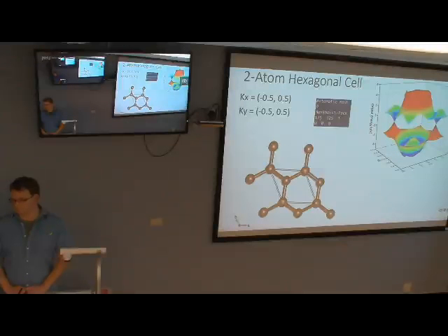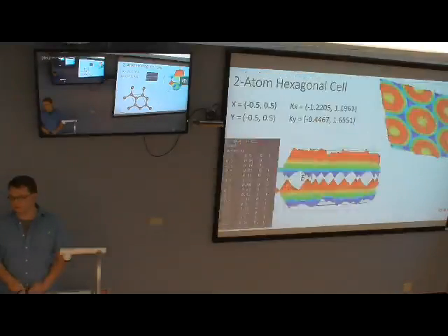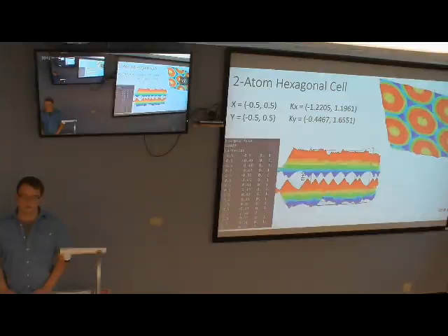Yes, and it especially does not characterize the points around all 6 Dirac points. Because here it shows explicitly 2 where they almost touch, right? But there should be 4 more. And so by manually choosing the k points, I can visualize all 6. One may need to fiddle with which k points, but the automatic doesn't seem to show quite as much as you can get.